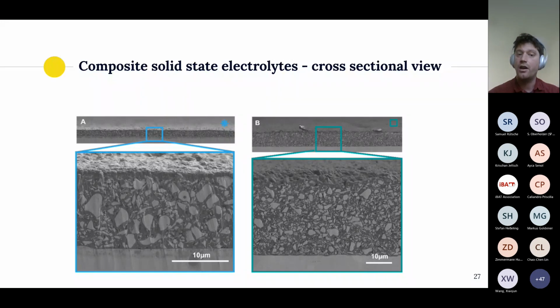The polymer phase is dark gray, the ceramic phase is light gray, and you can see that we are able to produce really, really dense and uniform thin layer composite electrolyte films. The left-hand side is, I think, just under 14 microns thick. The right-hand side is roughly 28 microns thick. And we have the ability to tune the layer thickness to our desire, or to the desire of our customers.